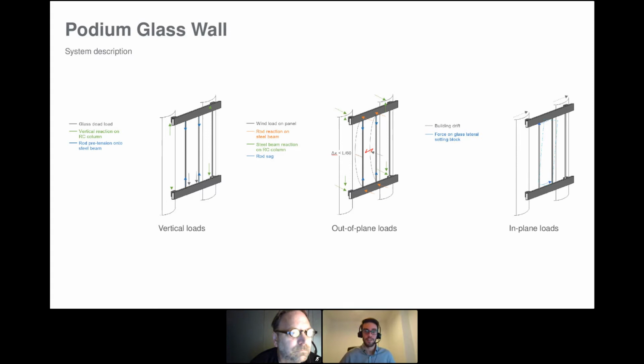How does the system work? Clearly for vertical load, that is mainly given by the prestress. The prestress goes to the top and bottom beam and becomes shear and clearly bending, and then is transferred back to the concrete column. For the lateral loads, the out of plane load, clearly the wind load blows against the glass panel, which mobilizes the rods, which become stiff when deflecting. So we are limiting the deflection to span over 60, and therefore the lateral load applied generates increased tension, which is again transferred back to the top and bottom beam, and then back to the reinforced concrete columns.